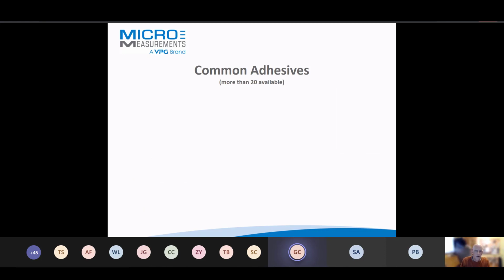We talk about using strain gauge certified products. We do more than 20 adhesives, for example. The most common that some of you will already be familiar with is instant adhesives or cyanoacrylate style adhesives. We produce M-Bond 200, which is a strain gauge certified adhesive. It's designed to go off in thin film. It doesn't have the plasticizers and fillers that are typical of high street cyanoacrylates. So don't be tempted to use a generic adhesive. Do use a strain gauge certified cyanoacrylate.